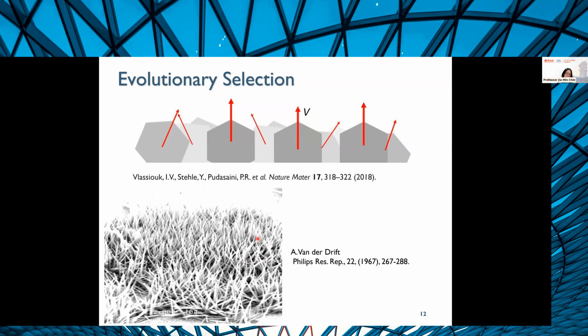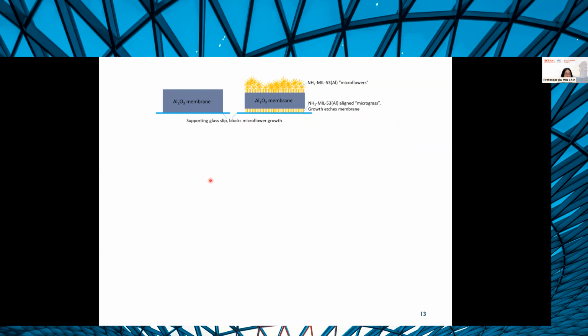So we thought, okay, maybe we could try to densify the structure, and maybe we could think about using the nano seed crystals that I showed you earlier, and effectively seed the lawn, if I want to push this analogy further. If we seed this lawn of AAO, maybe we could increase the density of this MOF grass that is growing and get them all vertically oriented. So what we did was we took some AAO membrane, we seeded it with these nanoseed crystals, and then we grew them where the AAO was supported on a glass slip.